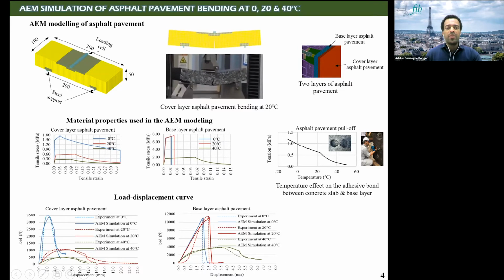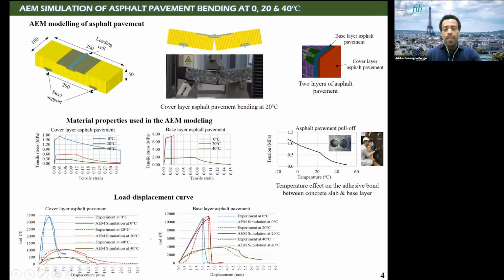So this is a load displacement curve, which is obtained from this bending experiment and simulation. This is the load in Newton, and this is the displacement. The first one is at 0 degrees centigrade for the cover layer. And the red one is at 20 degrees centigrade, and the last one is at 40 degrees centigrade. From this load displacement curve, you can clearly see that the asphalt pavement strength is significantly decreasing, but the ductility is improved. On the other hand, for the base layer asphalt pavement, the load displacement curves at 0 and at 20 degrees centigrade show almost similar behavior.